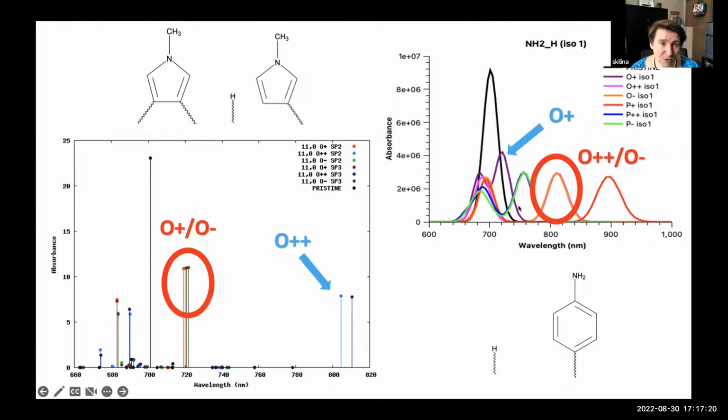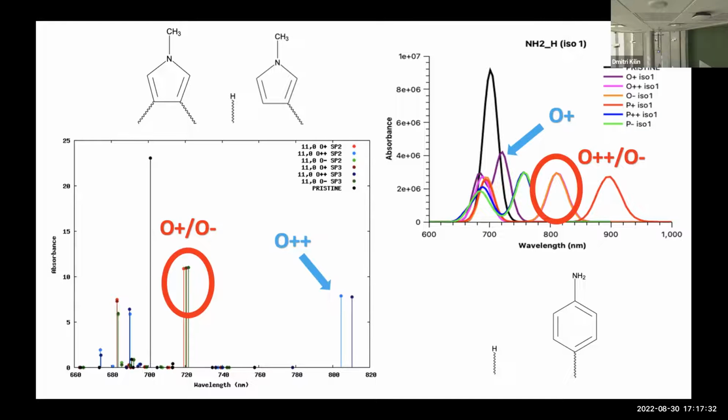And also, it's possible to imagine that maybe, total energy, by the way, Haley, have you taken a look at the total energy of these cases? I have not. Yeah, because you optimize the geometries, you immediately have these energies. So this is the first thing to compare, which of them thermodynamically is more favorable, right? Either it's sp2 or sp3, and how significant the difference is. Because if the difference between your ground state total energies is also in the order of kT, then it means that both species are possibly present, right? And then this redshifted peak would probably be just twice more intensive, because either this or this contribution will give you pretty much similar energy, with just a little bit increased line widths.